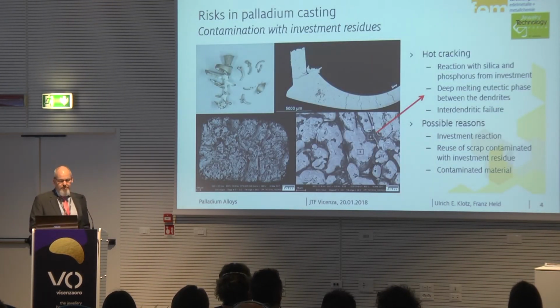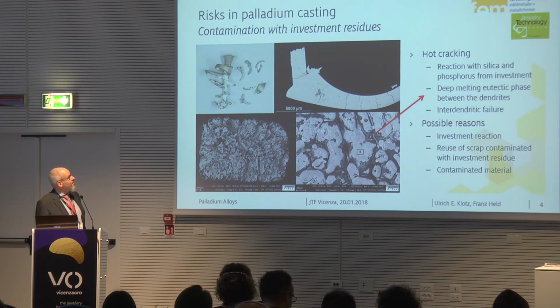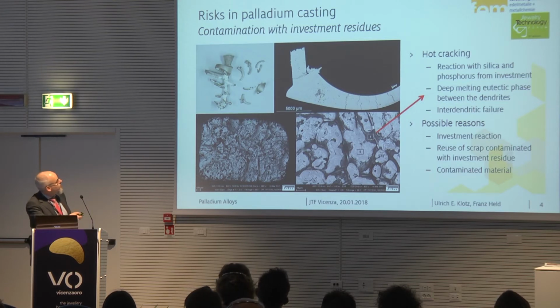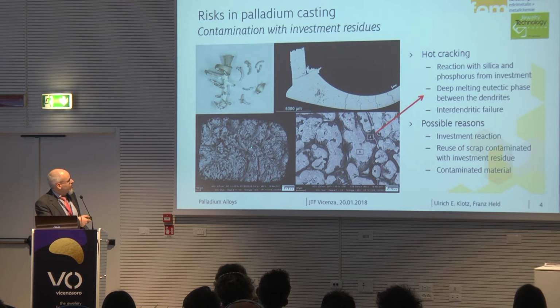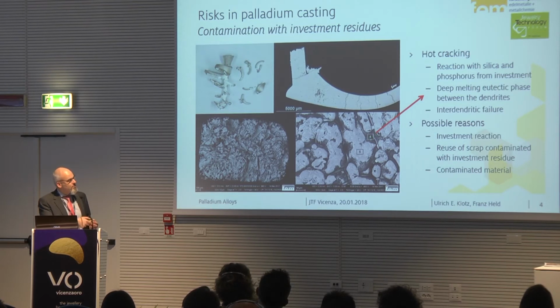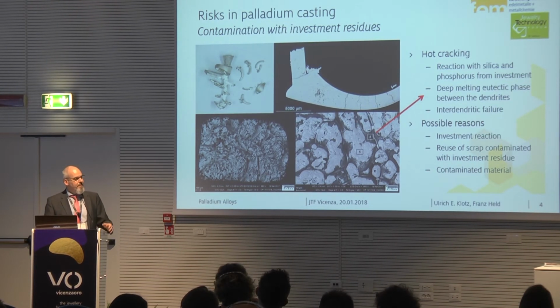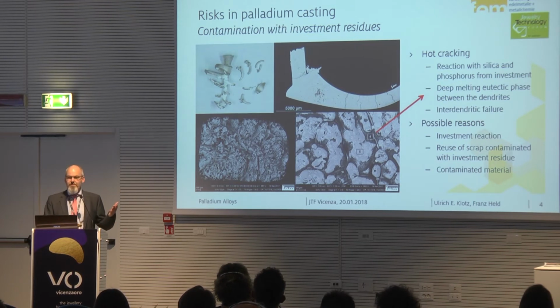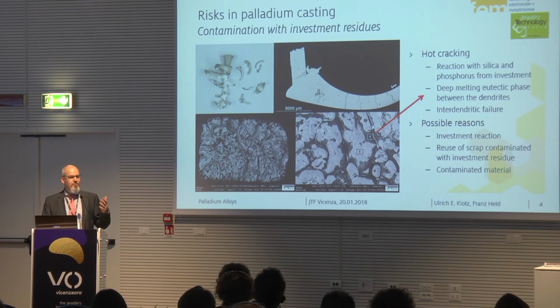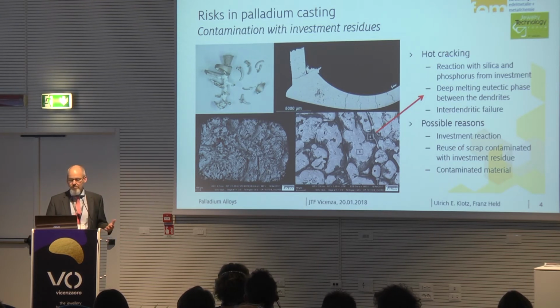The risk in casting of palladium is demonstrated by some pictures here. A completely broken casting tree where all parts are broken. You see in the metallographic cross-section they are full of cracks. In the cracks you see many dendrites, a picture you might know from this morning with these dendritic structures. If you have a closer look here, you see these dendrite tips, and we measured the chemical composition between the dendrites, and we found there are deep melting phases. The alloy has reacted in this particular case with investment material, and this resulted in a very strong embrittlement and complete fracture. So this is a risk in palladium, and such material cannot simply be remelted and reused. It has to be sent for refining.